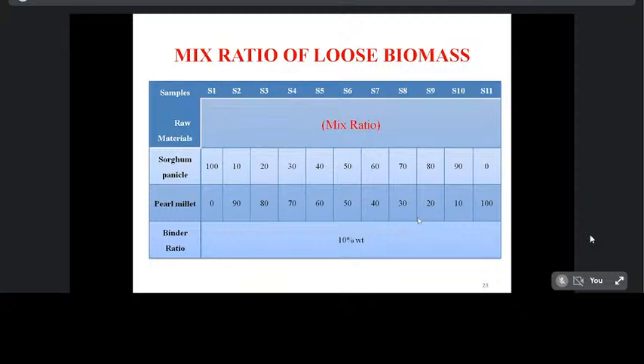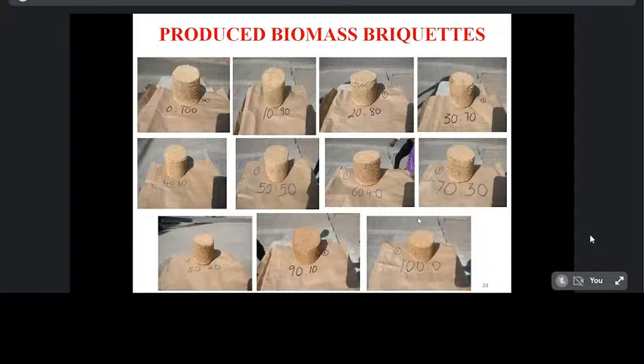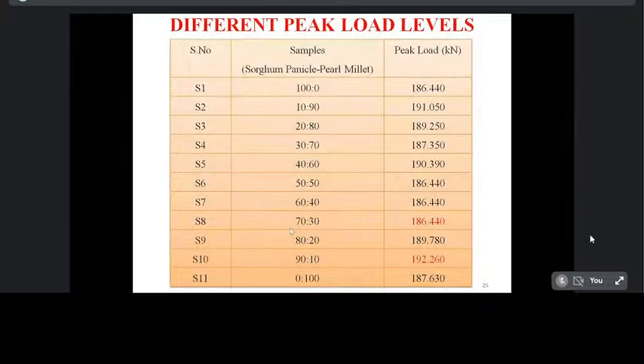The various proportions of sorghum panicle and Pearl millet samples were applied for the production of briquettes with different peak loads. This image shows the produced agro biomass briquettes with various mix ratios: 0:100, 10:90, 20:80, 30:70, up to 100:0. There are 11 solid biomass briquettes produced, shown in this image. While producing, we attain different peak load levels. We set a constant load of 200 kilonewton, but we get different peak load levels. From sample S1 to S11 it varied.